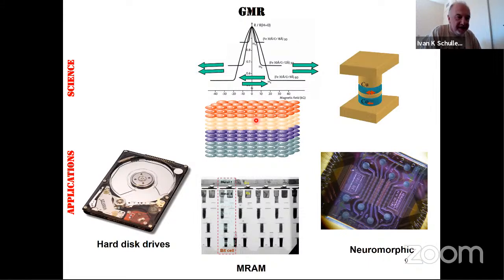This gave rise to another device, which is now being used actually in neuromorphic computing. This is what is called a spin torque oscillator. The spin torque oscillator is also a three layer device, for instance, two cobalt layers separated by copper. If you put a current through this device, because of the coupling of the magnetic moment of the current to the spin, one can turn around the magnetic moment of one of the layers with respect to the other, which gives rise to oscillations, and is nowadays used in neuromorphic computing. So these are the so-called spin torque oscillator devices.